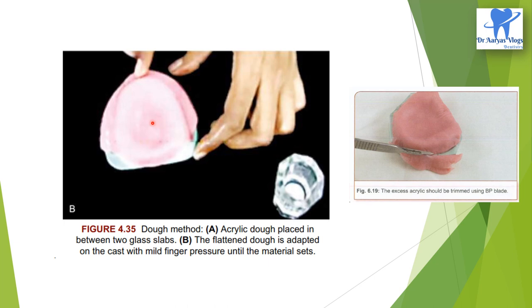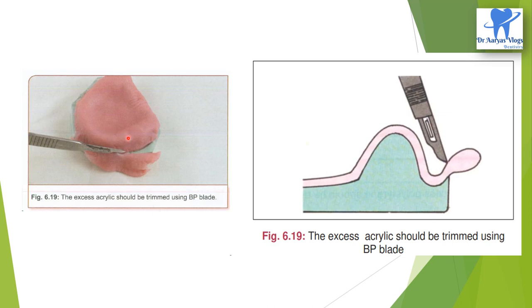Here the rolled sheet of acrylic is adapted over the cast from the center to the periphery, and it prevents the formation of wrinkles. Care should be taken not to apply excessive pressure on the ridge area because it might lead to thinning of the tray. The excess material should be cut out with a BP blade before the material sets. That is very important. If the material sets, then we cannot trim the excess using a BP blade. After cutting out the excess, the material should be held in position as shrinkage and warpage may occur during polymerization.